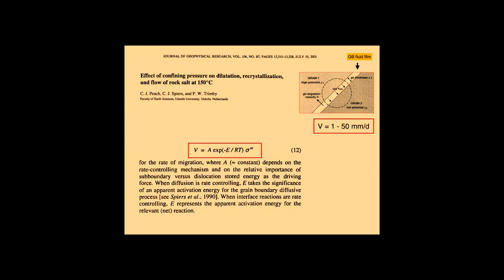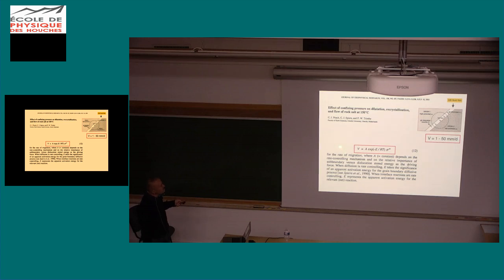There was a very nice paper by Colin Peach and Chris Spiers and Pat Trimby, who have derived an equation describing the velocity of these grain boundaries, and this constant in the equation here depends on the rate controlling mechanism. Of course, there are different candidates. You can have dissolution as a rate controlling step, you can have diffusion across the grain boundary, or you can have the precipitation.